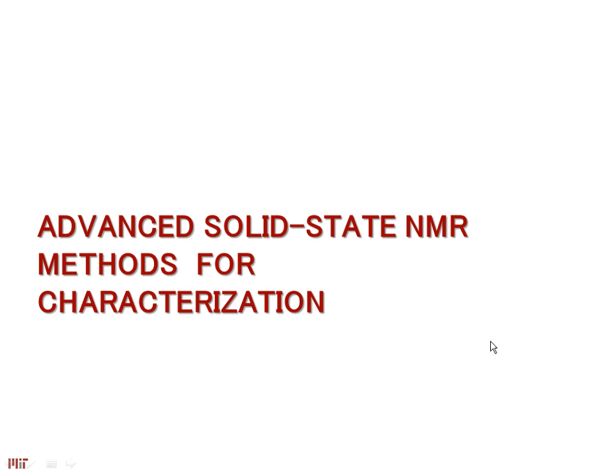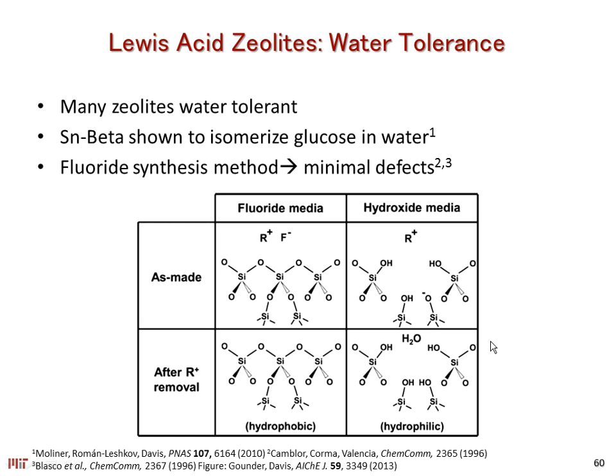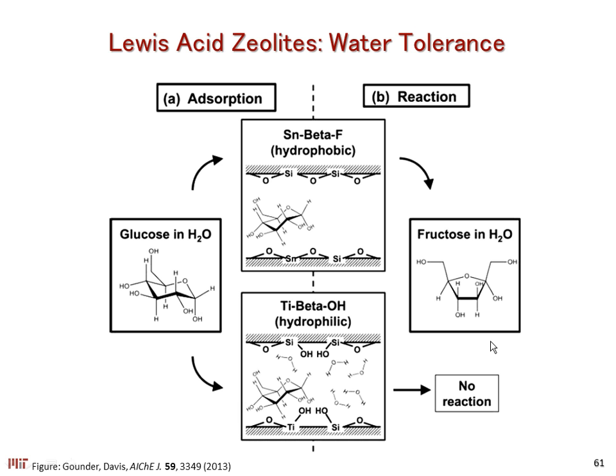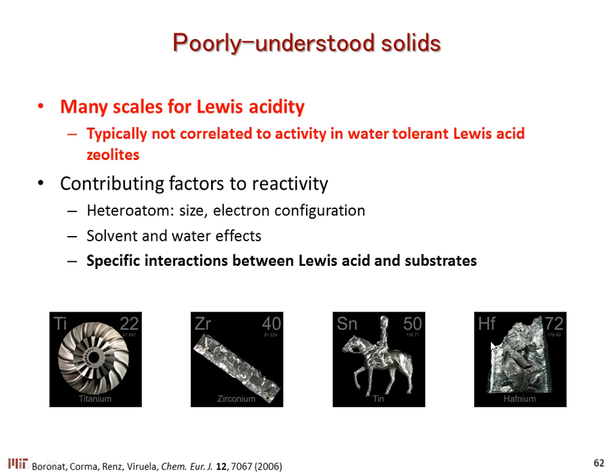And that's where I wanted to share with you some of this. We've been doing a lot of NMR methods or techniques to try to investigate what happens around this active site. And this stems from going back to the basics as to what determines the reactivity of some of these materials. We have to synthesize the zeolite in a fluoride media, and that ensures that we have no pore defects over there, so we have a very hydrophobic pore. And different heteroatoms will have different types of reactivity. So, coupling this hydrophobicity with the type of metal that you will have there really impacts reactivity and the stability of the catalyst. And there's a lot of different other factors that contribute to reactivity.